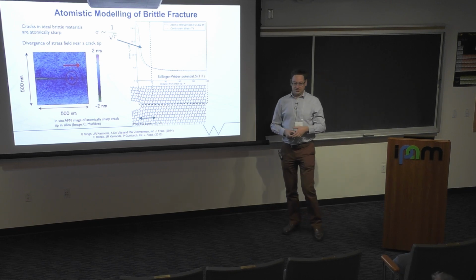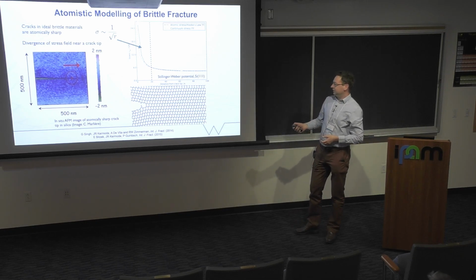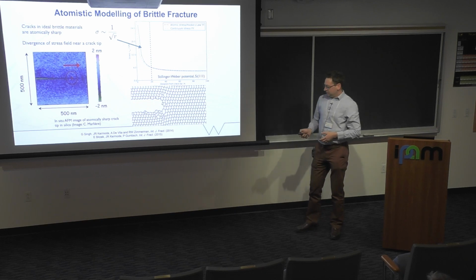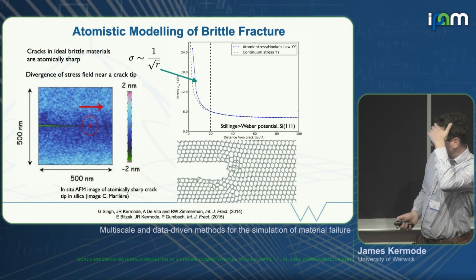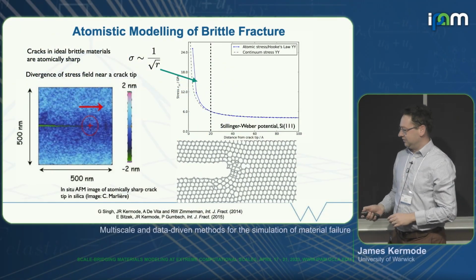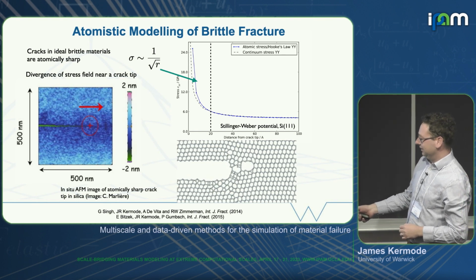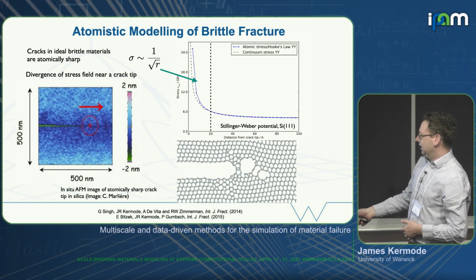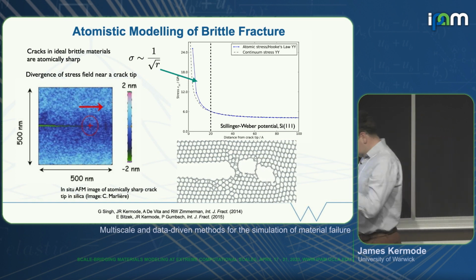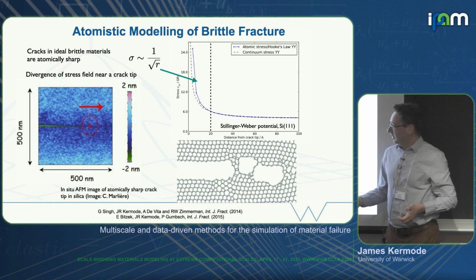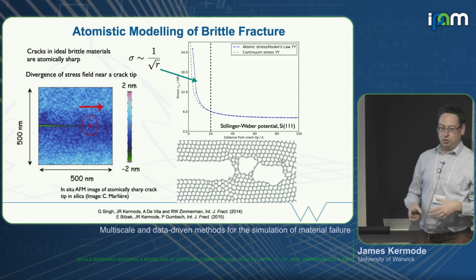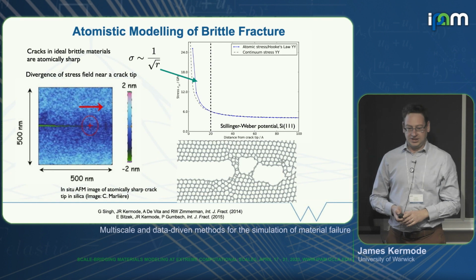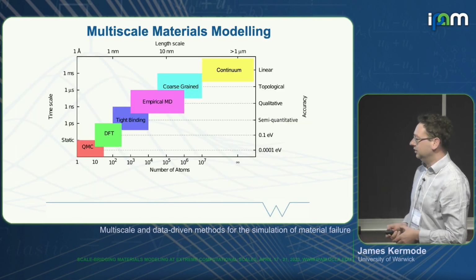We only really need to describe nonlinearities in a very small region, and so there's hope for doing that with an accurate method. However, if we use a simple interatomic potential of the kind that Christoph mentioned earlier on that involve two and three body interactions only, we don't correctly describe the dynamics of fracture. We massively overestimate the amount of energy that we have to put in. We don't recover this mirror smooth surface. We get emission of dislocations erroneously. We get a lot of mess, essentially. And I'll talk about some ways to remedy this, either by improving the quality of the potentials or by augmenting the description locally with something at a higher level than this description.